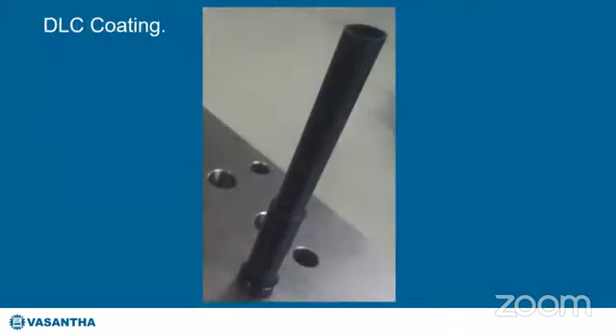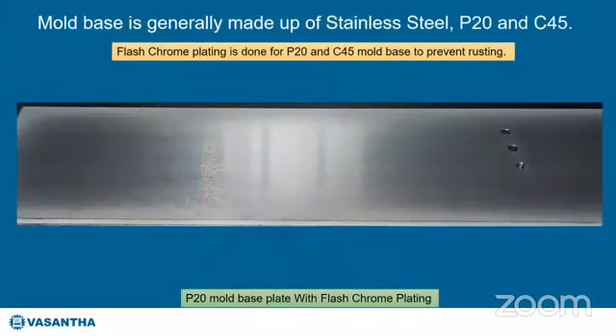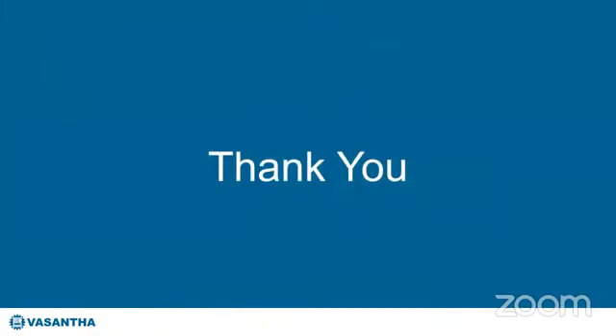After this comes the DLC coating. This reduces the friction and gives the anti-seizing property for the inserts. This is generally done for moving elements like sleeves. Then we have hard carbon coating for beryllium copper. And this is flash chrome plating, generally used for mold base materials made of P20 and C45. Stainless steel does not require flash chrome plating. So this was all about the manufacturing.